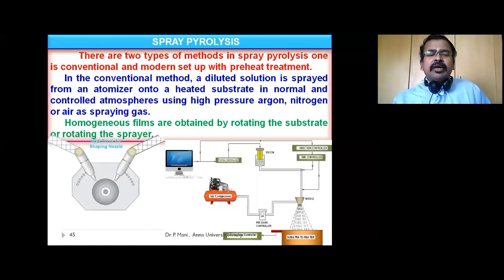Okay, spray pyrolysis. There are two types of spray pyrolysis: one is conventional, and another is the modern setup with preheat treatment. In the conventional method, a diluted solution is sprayed from an atomizer onto a heated substrate in normal or controlled atmosphere, using high pressure argon, nitrogen, or air as spraying gas. Homogeneous films are obtained by rotating the substrate or rotating the sprayer.